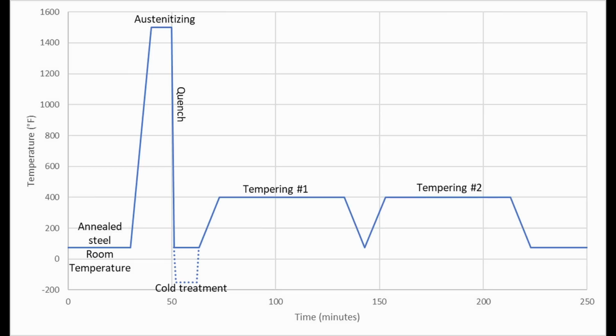So the first major step that we typically do in heat treating is to austenitize. This is starting with annealed soft steel, so the steel is ready for drilling and cutting, etc. Then we austenitize it. That just means heating it up really hot and you soak it for some period of time. Then next you quench the steel, which is rapidly cooling it, usually down to room temperature. Then tempering. This is reheating the steel to a lower temperature than austenitizing, usually something like 400 degrees Fahrenheit or 200 Celsius for 1 to 2 hours. And then you do that 2 to 3 times, cooling to room temperature in between.